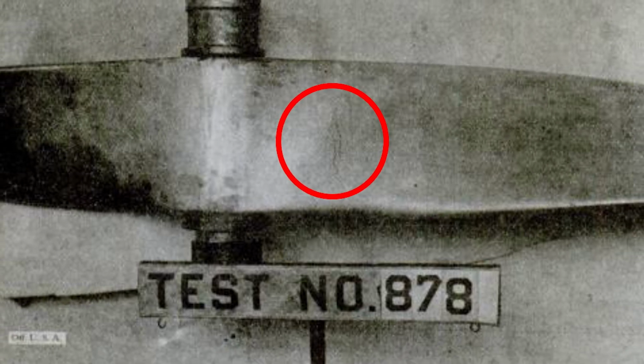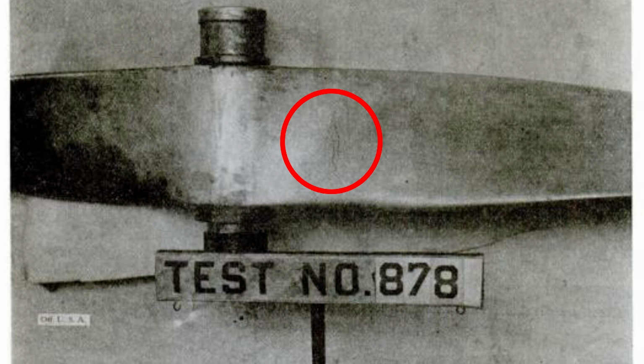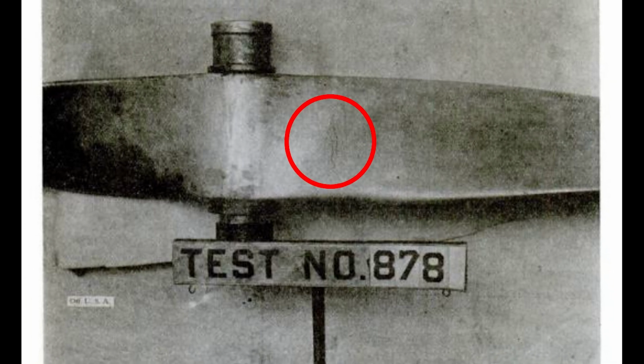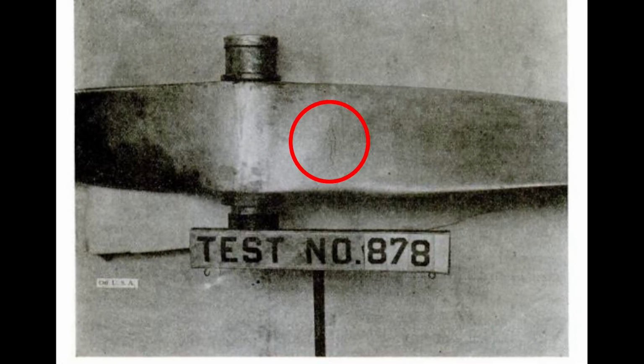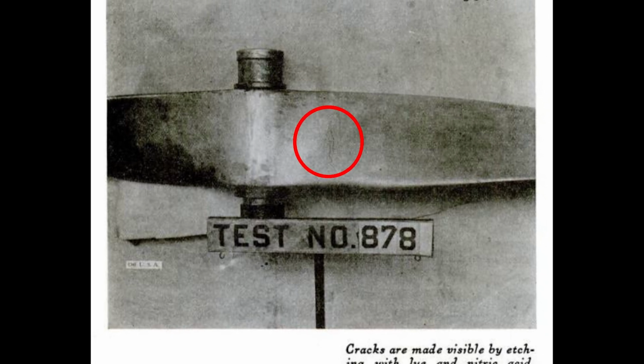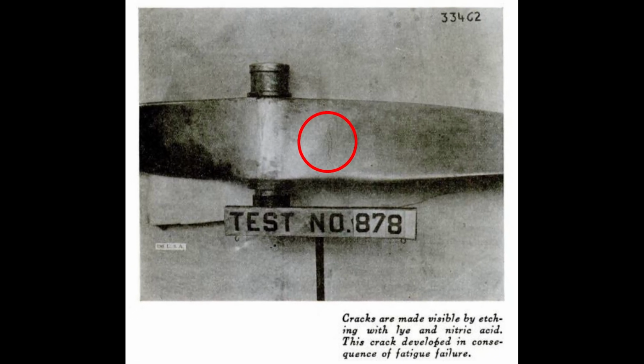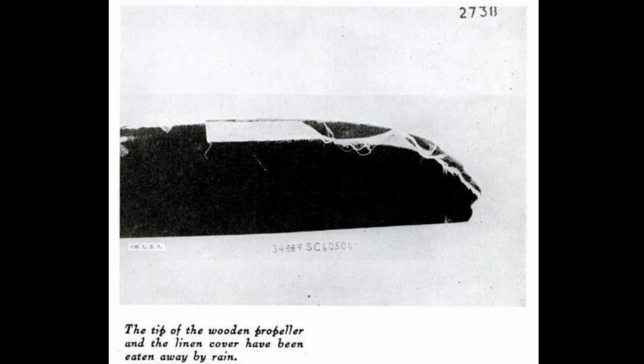To catch fatigue failure before it becomes serious, it is only necessary to examine the surface for cracks after a certain number of revolutions. For convenience, the inspection is required every 100 hours. Since modern propellers revolve at speeds frequently exceeding 2,000 revolutions per minute, 100 hours of flying is equivalent to more than 10 million revolutions of the propeller. Unfortunately, the cracks are not distinguishable, even with a powerful magnifying glass, without special treatment of the surface. Hence, in the examination, the surface is etched or eaten away slightly with a solution of caustic soda, then brushed with nitric acid and rinsed with water.